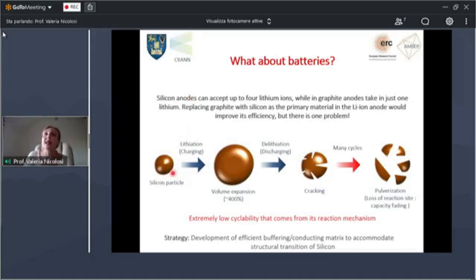The problem with silicon is that when you charge and discharge silicon nanoparticles, in this case, the particles go through a volumetric expansion and then compression of about 400% of their volume. When you go through that, the particles themselves start cracking and getting degraded. And then eventually, after a few cycles, the electrode starts pulverizing and losing its performance.